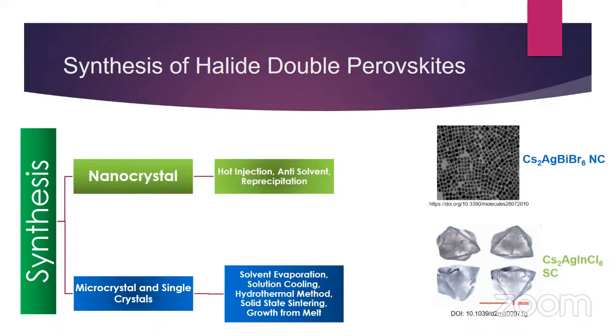So here are the synthesis procedures to produce double halide perovskites. These materials can be synthesized in both bulk and nano form. The nanocrystals can be synthesized by the hot injection method and anti-solvent reprecipitation. And in the bulk state, we can synthesize this halide double perovskite as a microcrystal and single crystal. The methods to produce microcrystals and single crystals are solvent evaporation, solution cooling, hydrothermal method, solid state sintering, and growth from the melt. In this diagram, you can see a TEM image of Cs2AgBiBr6 nanocrystals, and this is the image of Cs2AgInCl6 single crystal.